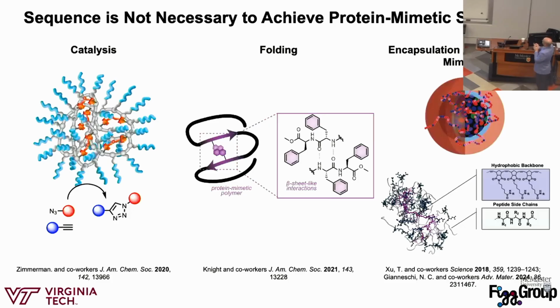And then this example is from Nathan Gianneschi at Northwestern, where they're polymerizing peptides. So they're using ring opening metathesis polymerization to polymerize these peptide side chains. What they're doing is taking peptides that don't work that well, polymerizing them to increase the avidity of the peptide, and now you actually have a really good drug. This is great and moving through clinical trials because essentially pharma has all these peptides that don't work that well. They can polymerize them and show that they actually make better drugs.